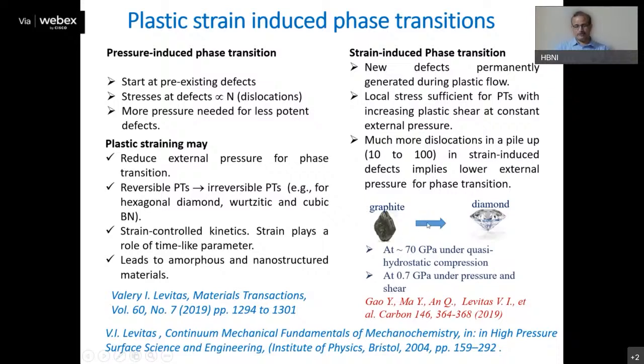There is one example recently published where it has been shown that graphite turns to diamond at pressures as low as 0.7 GPa under pressure and shear. Whereas under hydrostatic or quasi-hydrostatic conditions, people have shown that this transition takes place at as high as 70 GPa. There is a 2 orders of magnitude reduction in the transformation pressure. Of course, this was not the complete transformation. There was evidence of this transformation at some favorable positions in the sample, and it was verified by the TEM method. But if we know what kind of stress states lead to this kind of transition, we can actually plan for an industrial scale synthesis process where graphite can be turned to diamond at very low pressures. So this makes the study of plastic strain-induced phase transformation very important.